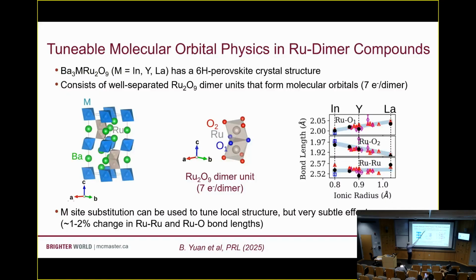Okay, so you get these ruthenium-2 oxygen-9 building blocks. They are face-sharing octahedra, and they're pretty well separated inside the crystal structure. Okay, so this is what we call a 6H perovskite crystal structure. And you can more or less think of these as well-separated dimers. And on each dimer, we have 7 electrons. Okay, so these form, I think, molecular orbitals.